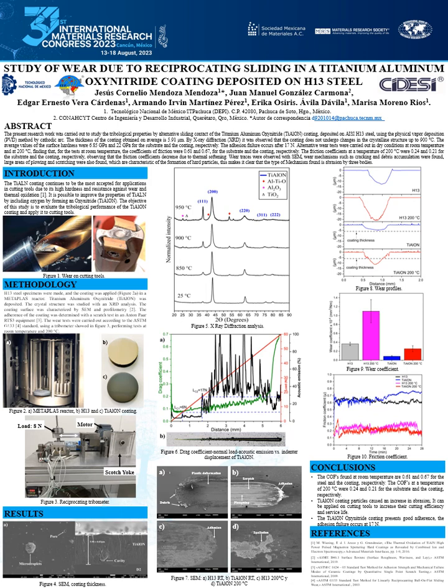The wear tests were carried out according to the ASTM G133 standard using a tribometer, shown in Figure 3, performing tests at room temperature and 200 degrees Celsius.